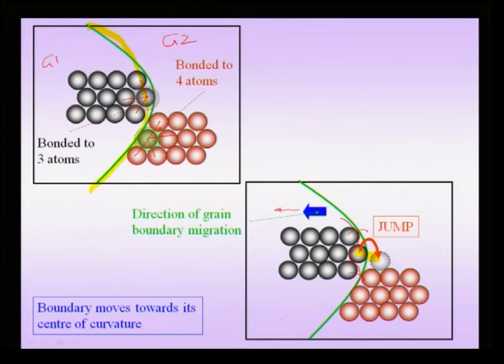And as you can note, suppose I had two grains, of course I am showing them very schematically here, a smaller grain vis-a-vis a larger grain. You can note that the larger grain has a lower grain boundary curvature, and a smaller grain with a lower radius of curvature has a higher curvature, and therefore the smaller grain would tend to shrink and the larger grain would tend to grow, and in the process my overall number of grains would decrease. That means the grain boundary interfacial area per unit volume would decrease.